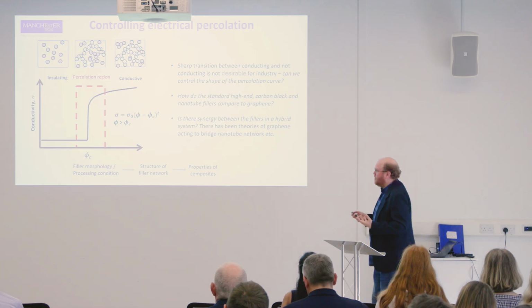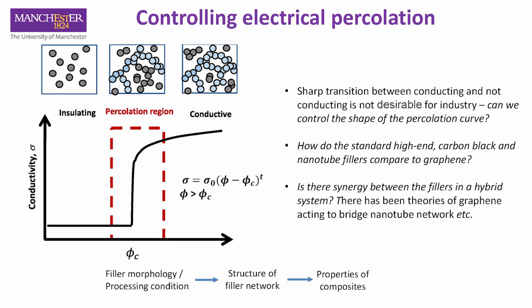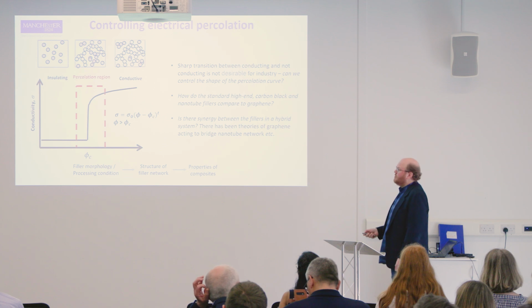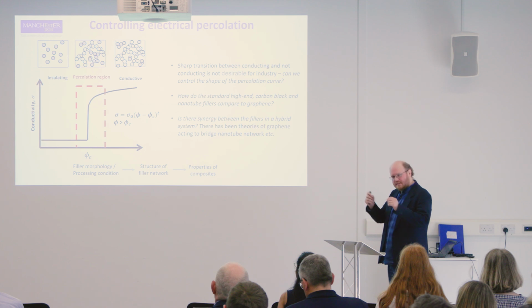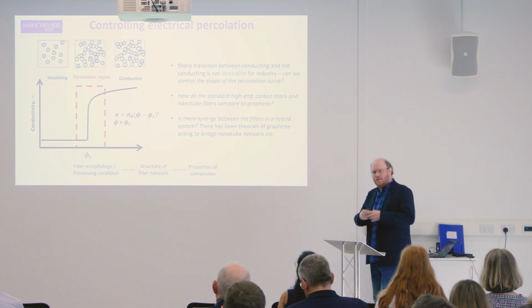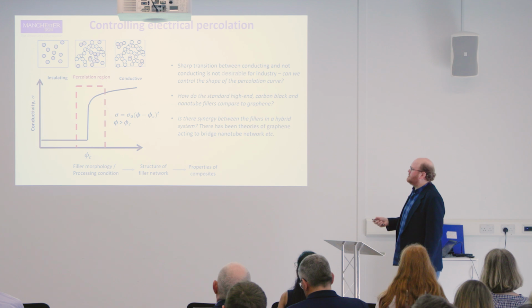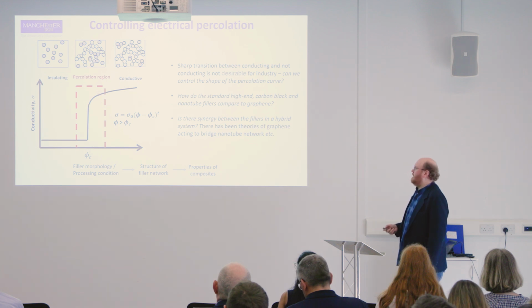For those familiar with this, you will have seen these electrical percolation curves. This is when you plot the conductivity of a material versus the loading of whatever additive you're adding. You have a very abrupt step change. At first you have an insulating material where your filler, your graphene, your nanotubes, your carbon black, whatever it may be, is dispersed in your matrix. The particles are not in contact with each other, so there's no conductive pathway and it's still completely insulating. As you keep adding more filler, you reach a critical threshold, this percolation region, where all of a sudden you have a continuous pathway through your composite, and now you have electrical and thermal conductivity through it. So the conductivity shoots up and then more or less flatlines.